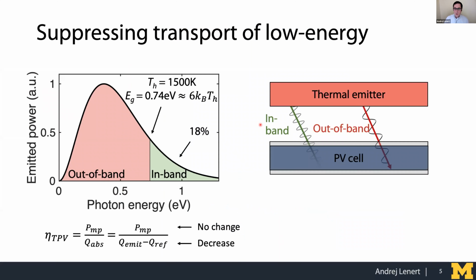So the metric that we were going after in our group is to improve spectral efficiency, so the ability to convert this broad spectrum that's radiated by a heat source. And I just want to note, without going into too much detail, that TPVs are best suited at converting the thermal tail of the blackbody distribution or Planck's distribution. That's because as we push the band gap higher, we can produce higher voltages, and then we're less susceptible to non-radiative recombination and ohmic losses. And these are very important losses in TPVs. So as we push the band gap higher, these become less important.